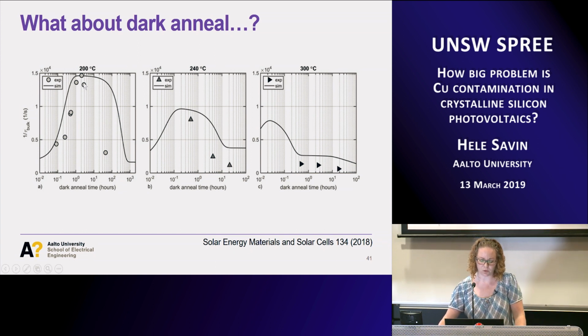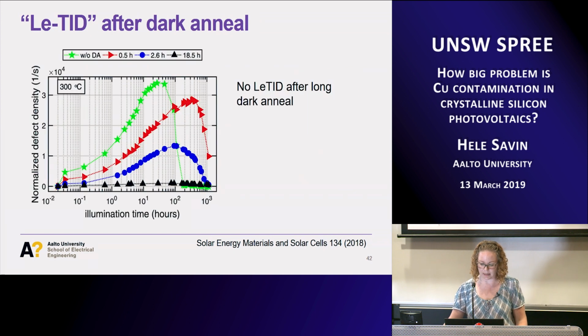So if we would take one of these samples, which for instance are here or here, when they seem to have already lots of precipitates, and then we start shining light on them, we probably just increase the LID. But if we use some of these spots here, where the copper has had enough time to diffuse to the surfaces and isn't a problem in the bulk anymore, and then we take this kind of sample and expose it to light, our hypothesis is that it won't show LID. And this is exactly what we see.